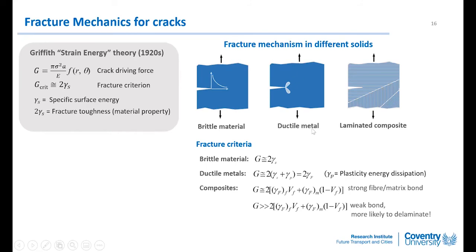The middle one is ductile metal. That is our aluminum, titanium, steels. You get 2 beautiful plastic zones at the crack tip, and they absorb energy. This butterfly shape is actually the plasticity energy dissipation zone. That increases the fracture energy by a factor of gamma P. That means plasticity, so the fracture toughness increases enormously. So ductile metal can tolerate crack growth, can tolerate a crack. The last material is laminated composites. You've got a 0-degree fiber, a 90-degree fiber in the next layer, and 45-degree in the further layers. In that case, it requires defining the fiber volume fraction and the matrix.